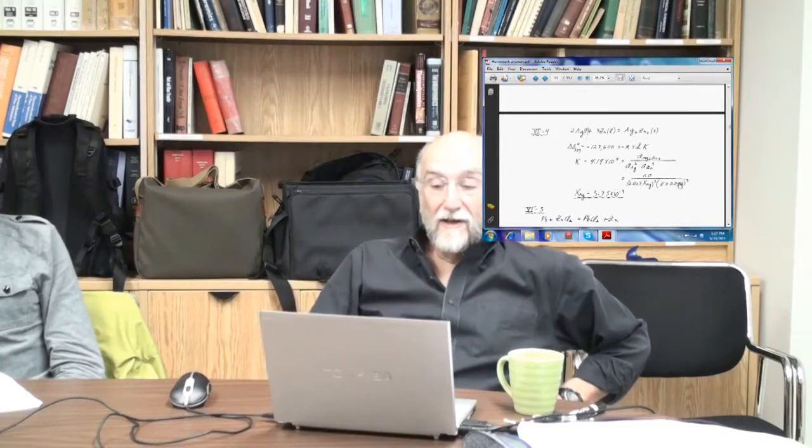If you add more zinc, then you will end up with more zinc dissolved at the end, and you bring down the mole fraction of silver, but you increase the contamination with zinc. So you're replacing the silver by zinc. Okay, so this is what you're doing. You're bringing the silver down to 10 to the minus 4, and now you've got 1% zinc in there. You can add more zinc to get this lower, so you try to figure out what you need and then add the minimum amount of zinc necessary to get it down to that.